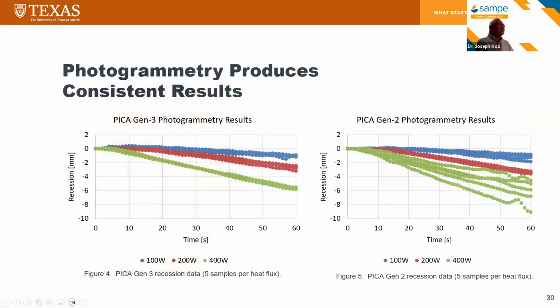Okay, so this is some data that we are collecting on PICA Gen 3, and you can see we use different heat fluxes, and we were able to use photogrammetry and calculate the recession, and we were comparing Gen 3 and Gen 2 data, and that's what we are able to see. These kind of data are very reproducible. We received the PICA Gen 2 and PICA Gen 3 material from Spirit, from FMI, and we work very closely with the company. They sent us the material, and we were able to conduct a fair amount of testing.